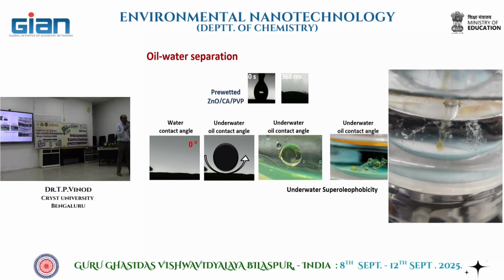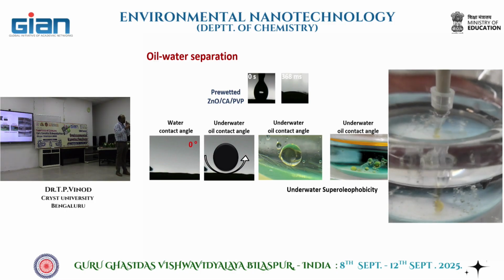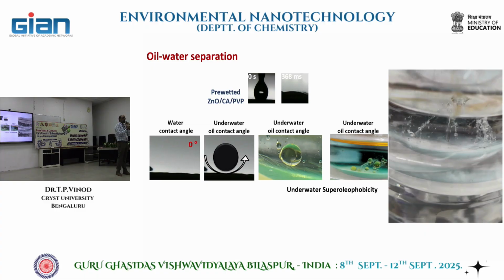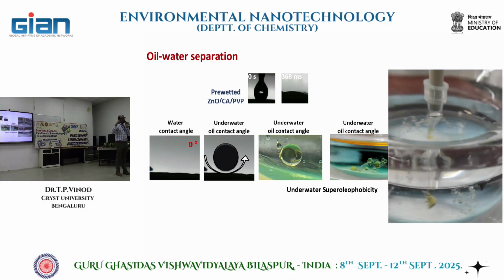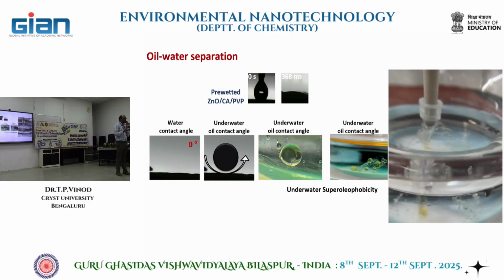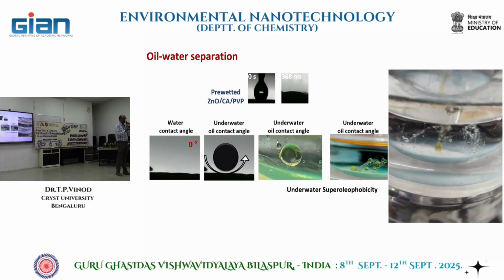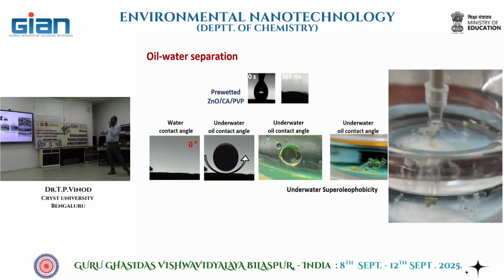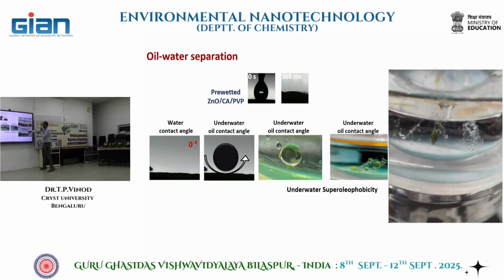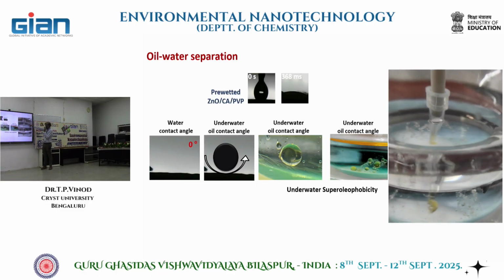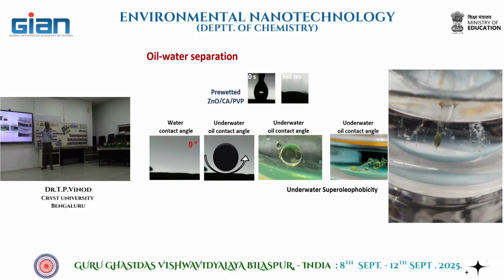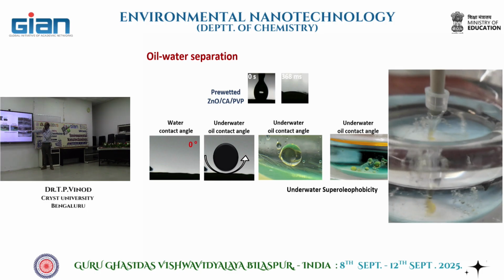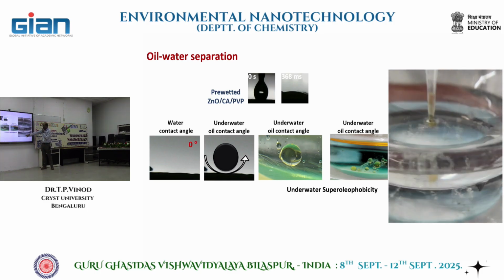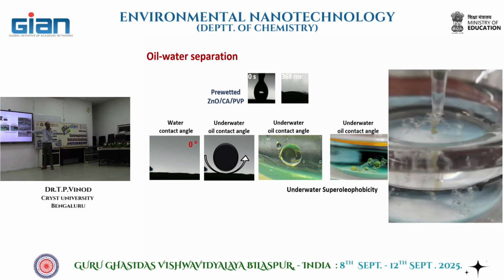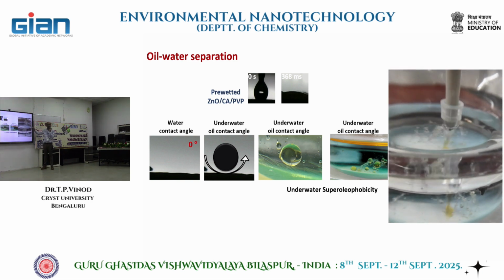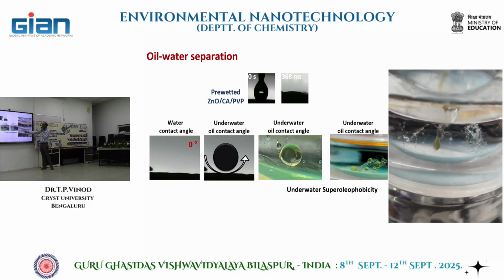So and then normally when we measure this contact angle for checking hydrophilicity or hydrophobicity, we do it in the ambient condition. But for this application, you need to have this membrane immersed in water, or water will be above it, right? So we immerse that film over here, and we try to put an oil droplet onto it. Okay, then that oil droplet you can see is never touching. I mean, it's never wetting that surface. It's actually repelling the oil droplet. So we have this underwater super oleophobicity.